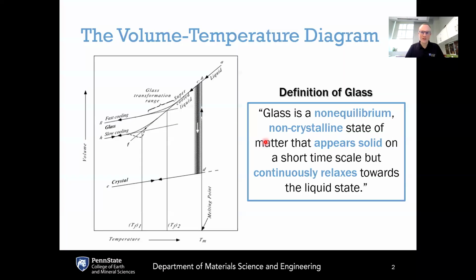So remember from the last chapter, from chapter 2, we introduced this volume temperature diagram. And what we saw from that is that if you have any liquid up here in the upper right-hand corner, if you are able to cool that liquid fast enough to avoid crystallization in this gray shaded region, what you will get is a supercooled liquid. It is this thermodynamically metastable state that upon continued cooling would give us the glassy state. And the glass here is a solid-like material with a liquid-like structure.